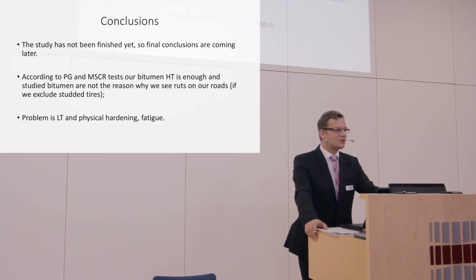As I said, we cannot draw final conclusions at this moment, but some preliminary conclusions: according to PG and MSCR tests, our bitumen's high temperature grade is covered enough with our studied bitumen, and bitumen is not the reason we see ruts on our roads if we exclude studded tires. We can clearly see that our bitumen problem is low temperature and physical hardening, also fatigue properties.